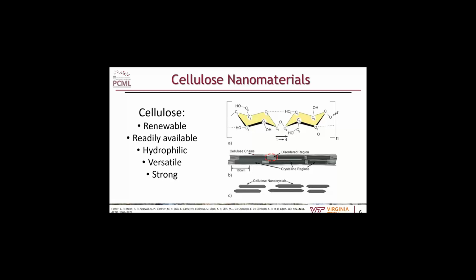If you instead take your cellulose material, whether it be a log or a paper filter, and put that paper filter in something like sulfuric acid, you can effectively eat away all of the disordered regions, the amorphous sections, and the tightly packed sections that make up the dense crystalline regions will remain, because the acid has a hard time getting in between the tightly packed layers. You get these fairly regularly shaped cellulose nanocrystals.